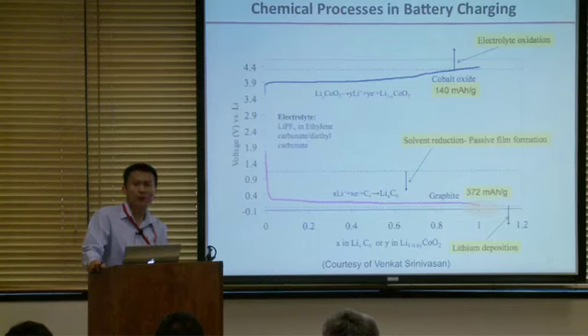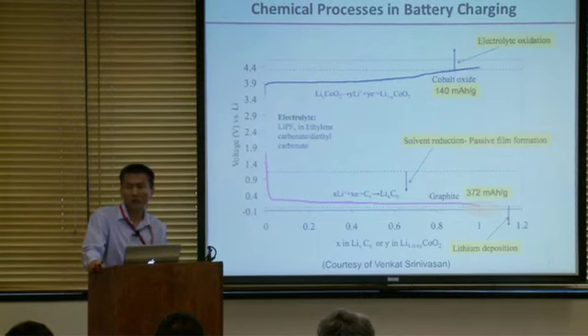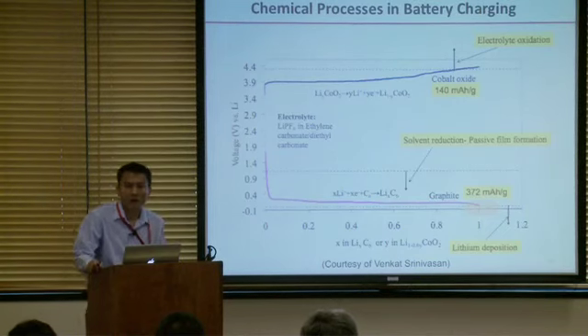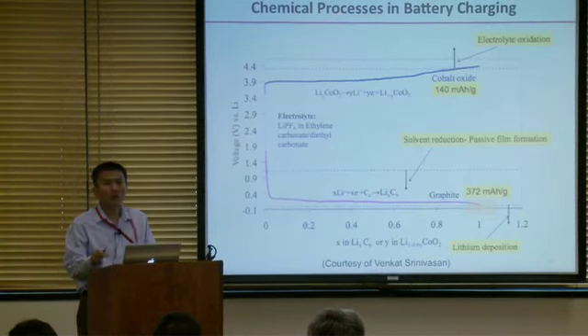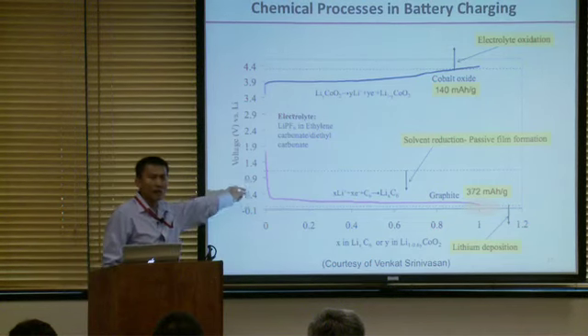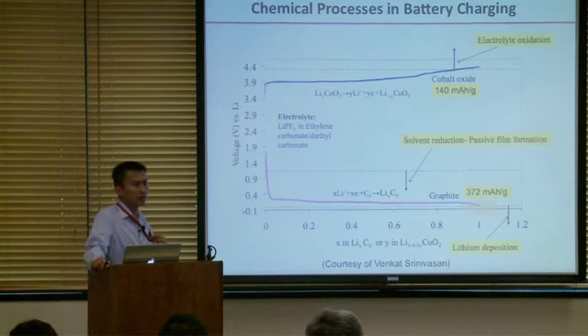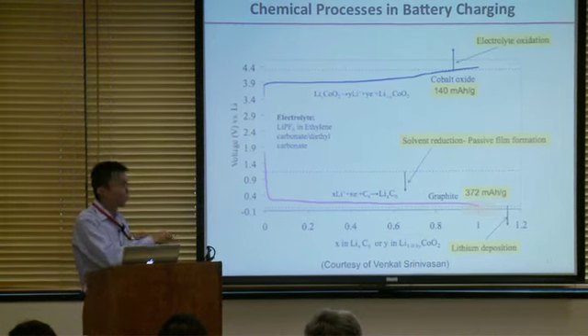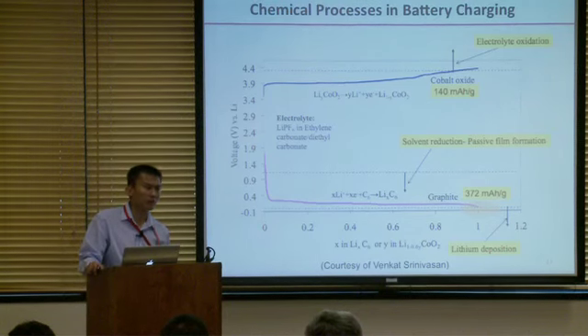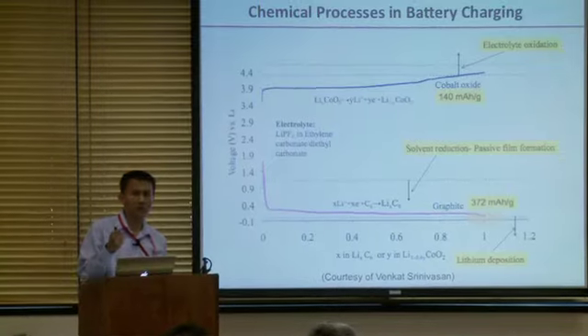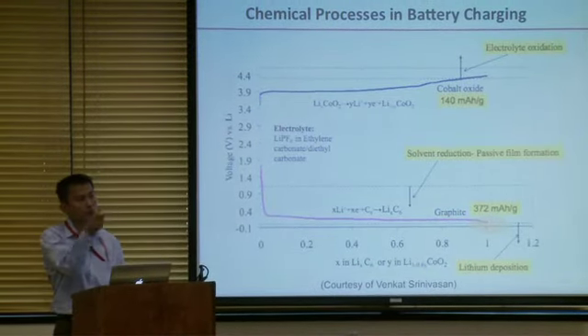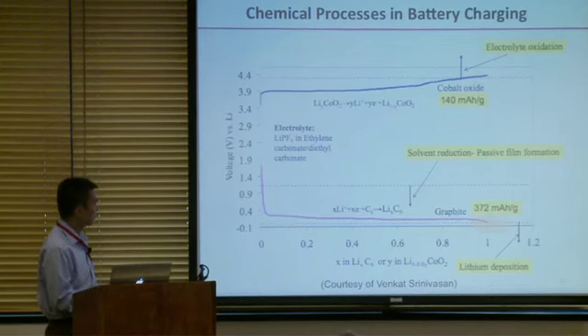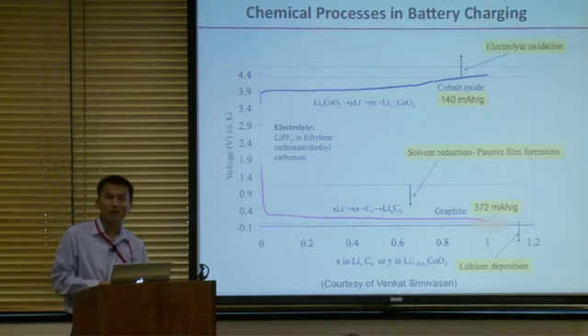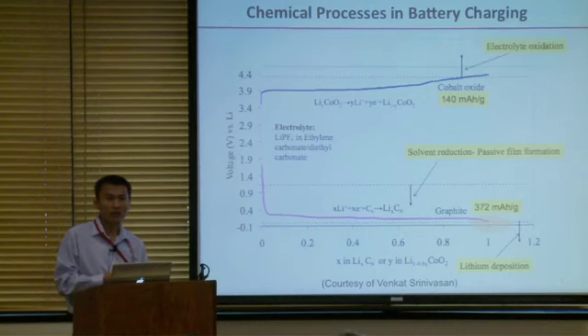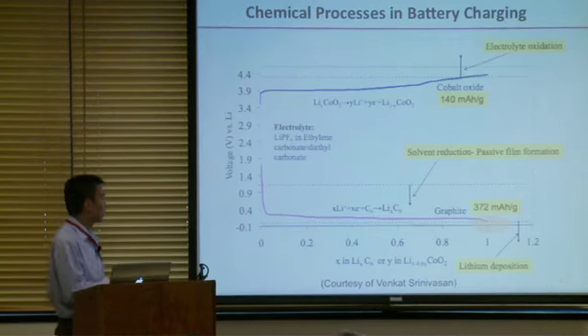You need this film to build very nicely. And it took so many years for the battery industry to really know how to build a nice film. At the end, you want this film to self-passivate. You don't want the electrons from the negative electrode to go onto the organic molecules anymore. You don't want that. And you want this film to be ionically conducting. Lithium can still come in from the electrolyte, but it's electrically insulating, so electrons cannot transfer from the electrode to the electrolyte solvent to stop the side chemical reaction. If you keep having side chemical reaction, you consume your electrolyte and you consume your lithium. At the end, the battery is dead. That turned out to be very important.